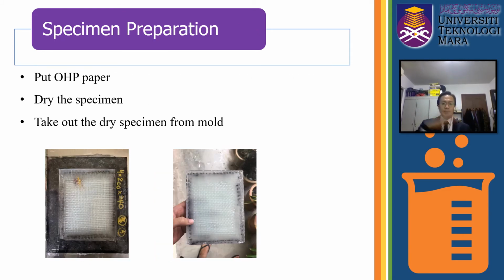Next, I put OHP paper on the top of my mixture to ensure that I can compress it until it becomes 4 mm of thickness in specimen. Why do I put OHP paper? It is because OHP paper is one of the materials that will not stick to the epoxy composite when it dries. After I put the OHP paper, I will dry the specimen for 1 day to ensure that the specimen is totally dry. After 1 day, I take out the dry specimen from my mold as the picture shown.